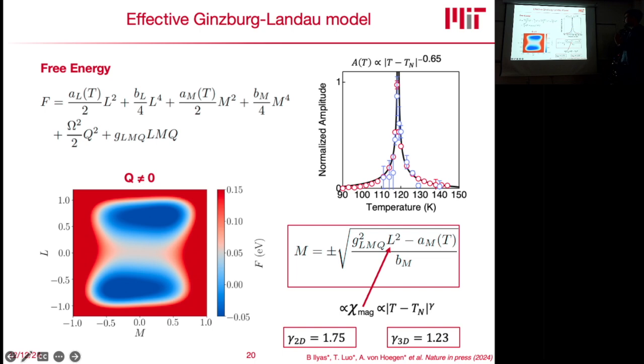The thing is, in this case we can basically only... the sign of this coupling term is always preserved. As soon as you switch L, if you translate L one up, the lower half is redundant, as you said, because if you go from L to minus L, also the sign of Q will change, right? Because also the Raman mode will follow this translation, and so therefore the sign of Q will also change. So M is always positive. So you're fully right. The bottom half of this figure is redundant in this case. Yes. Fully right.